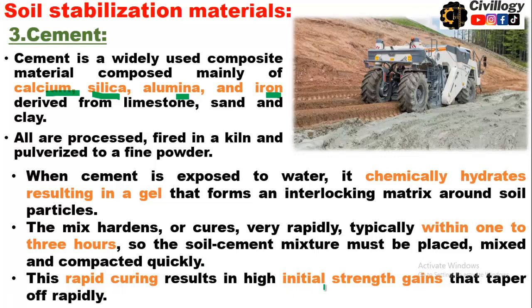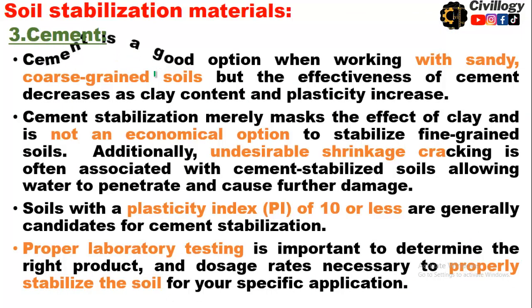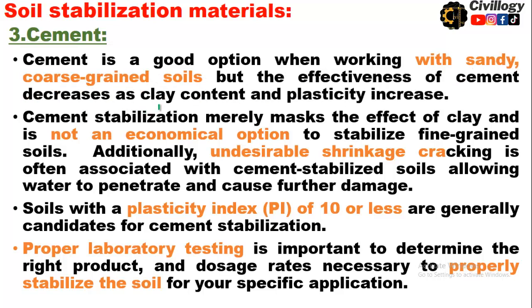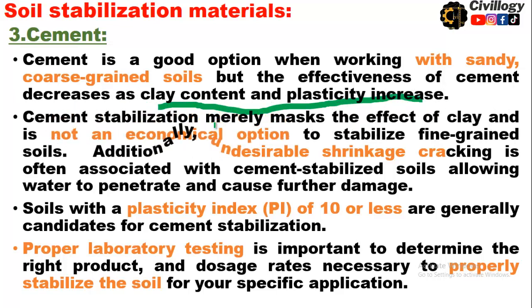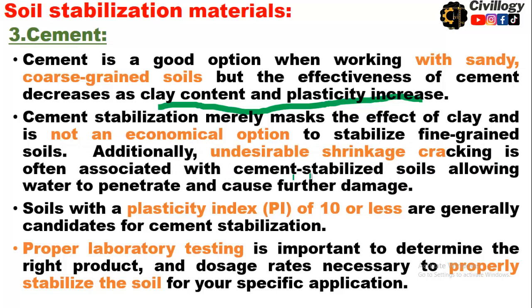This rapid curing results in high initial strength gains that taper off rapidly. Cement is a good option when working with sandy, coarse-grained soils, but the effectiveness of cement decreases as clay content and plasticity index increase. Cement is not suitable for materials having high clay content. Cement stabilization merely masks the effect of clay and is not an economical option for fine-grained soils. Additionally, undesirable shrinkage cracking is often associated with cement-stabilized soils, allowing water to penetrate and cause further damage.